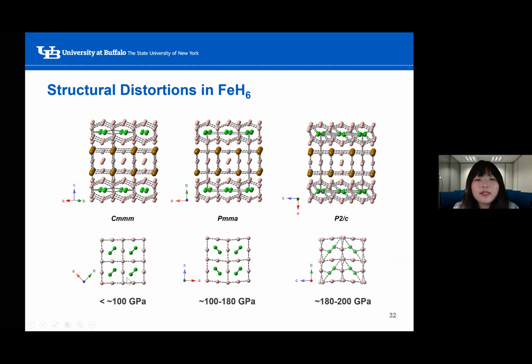Moving on to FeH6, we found three structures. We found the known structure Cmmm that's stable below 100 GPa, and we found a new structure Pmma that's stable up to 180 GPa, and we found another P2/c phase that's stable up to 200 GPa. So all of these structures, again, are comprised of the cubic-like FeH3 layers, but separated by not only atomic hydrogens, but also molecular hydrogen layers.